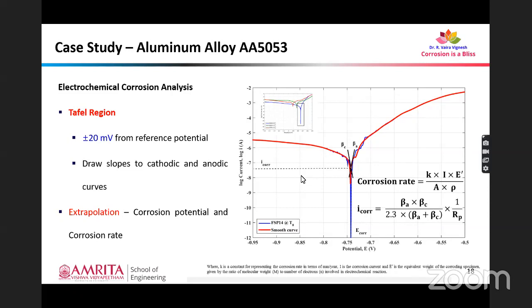This could be done using MATLAB or some software that is readily available from internet sources. So this was done using MATLAB. What we have to take is the potential drop region where the current is very, very minimal. That is our reference potential. From that, within the range of plus or minus 20 millivolt, we have to draw slopes to the cathodic and anodic curves. Where these cathodic and anodic curves intercept, that point is going to be our corrosion current. And obviously this intersection point will correspond to a potential. That potential is termed as corrosion potential. This process is called extrapolation, because we extrapolate the values to get I_corr and E_corr.